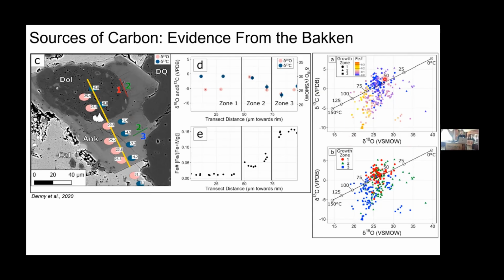And now these are colored by the iron content of the individual sample. The darker colors here are lower iron content, and the lighter colors are higher iron content. So the most iron-rich samples have the most depleted delta 13 of carbon, suggesting there's more organic influence where we have more iron in the carbonates, which is exactly what we were proposing for the Sappington, with those later stages being derived from the shales.